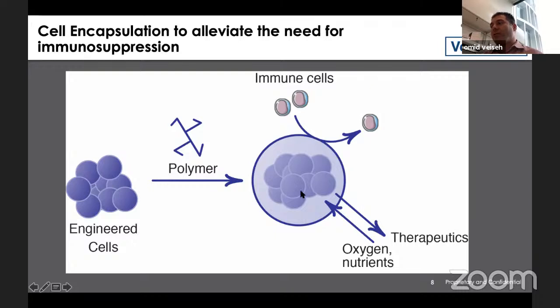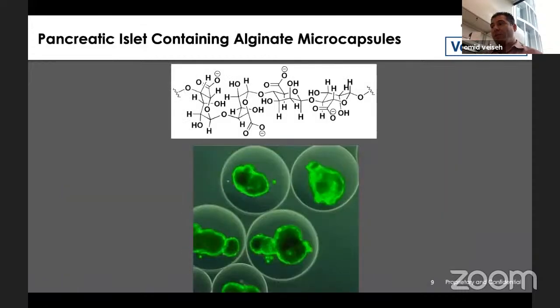If this matrix is porous so that oxygen and nutrients can get in and out, and the therapeutics, which in this case is insulin, can get out, this could be transformative for the patients. It alleviates the need for having to do immunosuppression. And one of the materials that people have been exploring for this application for many years is alginate polymers. The reason why alginate is preferred is because you can create a hydrogel matrix around cells using really gentle reactions, such as chelation. It naturally chelates with divalent cations, such as calcium or barium, and it forms a stable structure around the cells, which is actually a porous matrix, such that the porosity is tuned to exclude immune cells and at the same time allows for diffusion of nutrients and oxygen in and out.